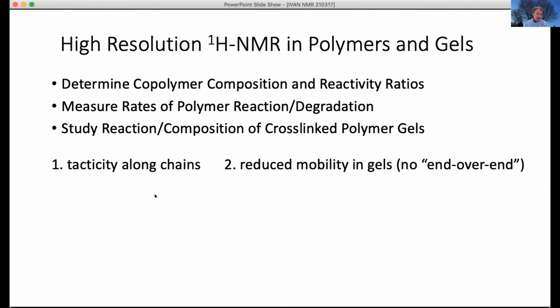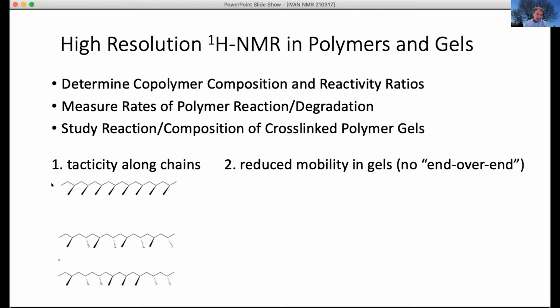The problems we face in practical terms are, as you know, when you look at an acrylic or a styrenic polymer, you've got different stereochemistry that can happen along the backbone: isotactic, syndiotactic, alternating, or random tacticity in an atactic system. That leads to scrambling of the local environment and broader NMR peaks compared to small molecule NMR.